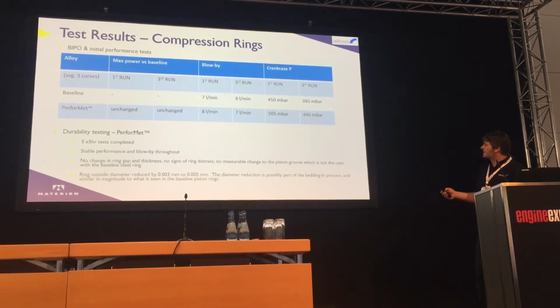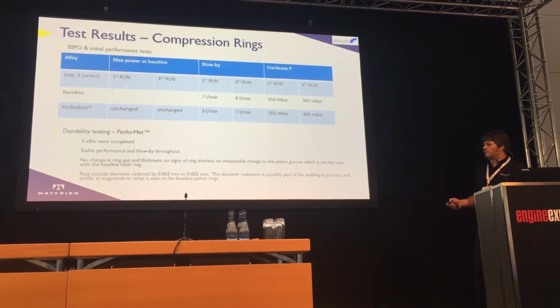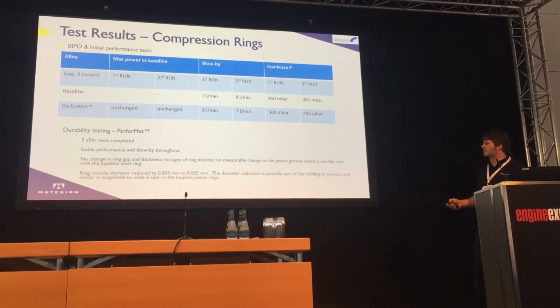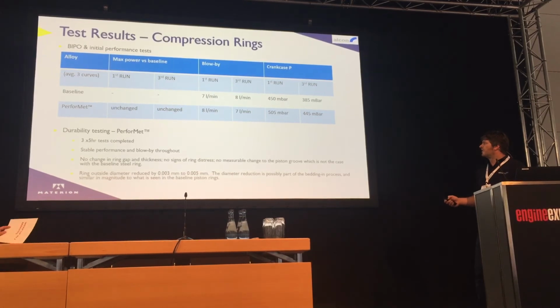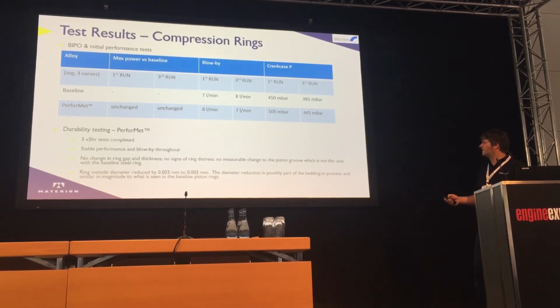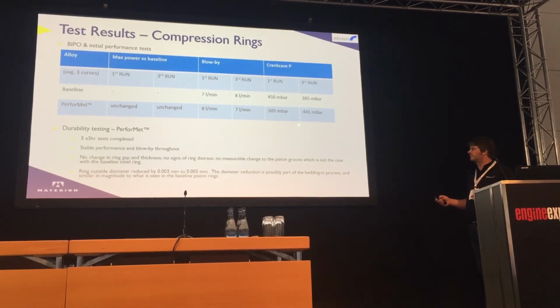Compared to the baseline test, we were measuring blow-by, crankcase pressure and performance. We really measured no difference in performance at all. In terms of blow-by, very, very similar numbers again. If anything, I'd say the blow-by was more stable. Crankcase pressure remained good as well throughout the 3 endurance tests.